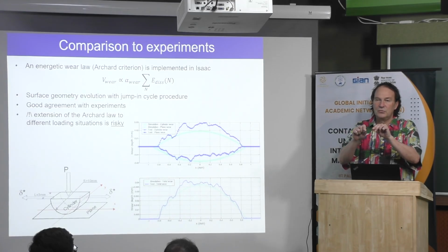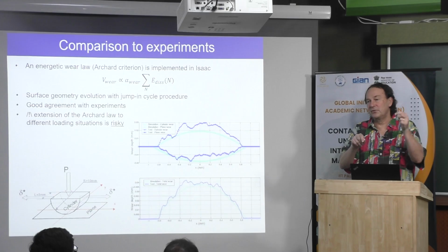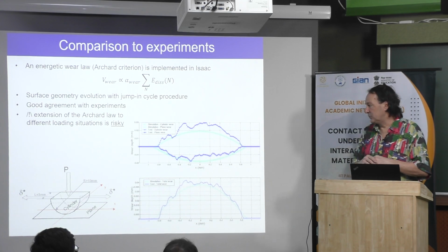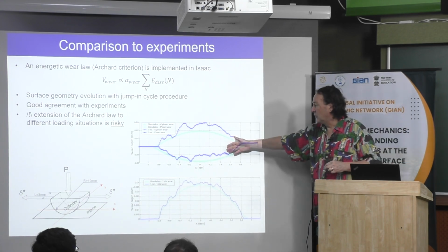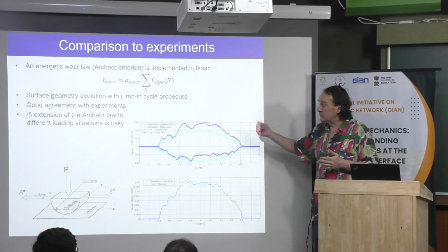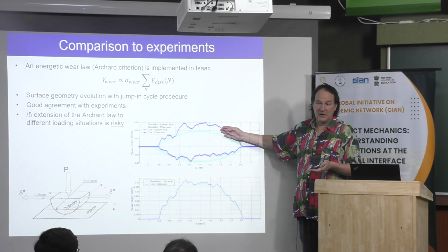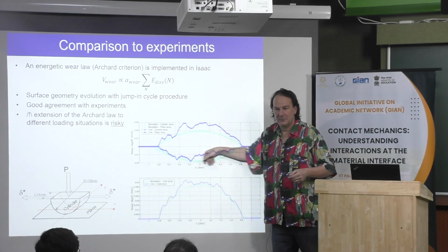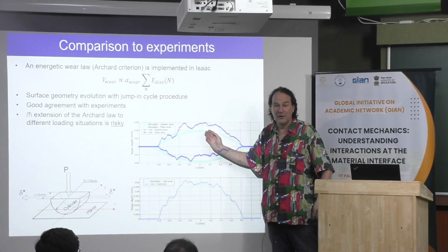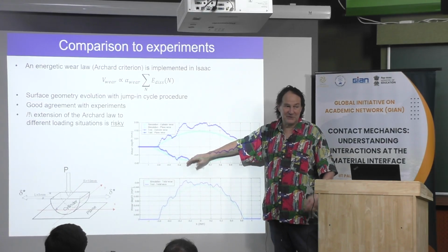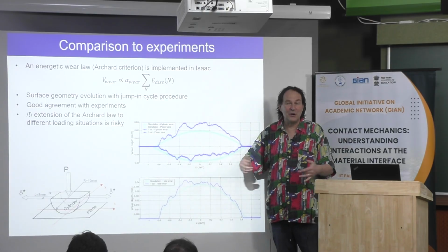That was to make some measurement of the flow of debris for the modeling to take into account the effect of debris. But when you have the same material, you can see globally you have a good agreement. In fact, because we consider the wear coefficient coming from the experiment, it's normal to have the same integral. If you calculate the volume, normally for the experiment and for the simulations, you should have the same wear volume because the wear coefficient is coming from that.